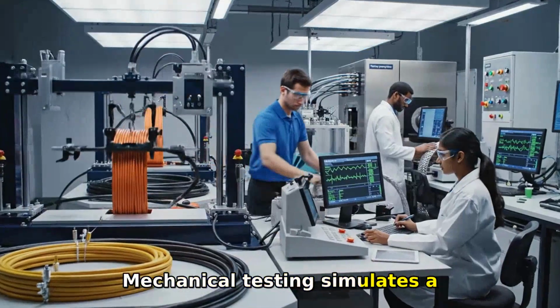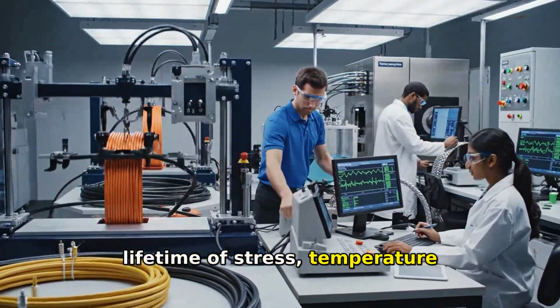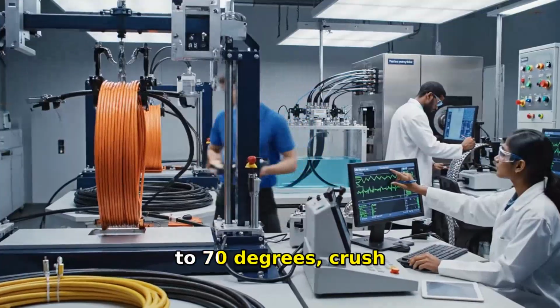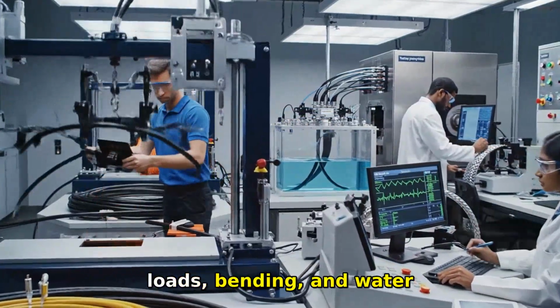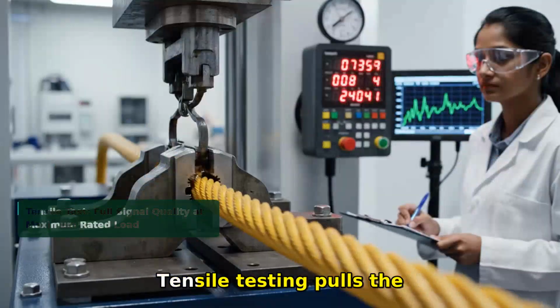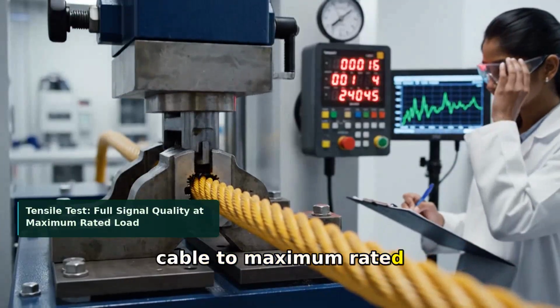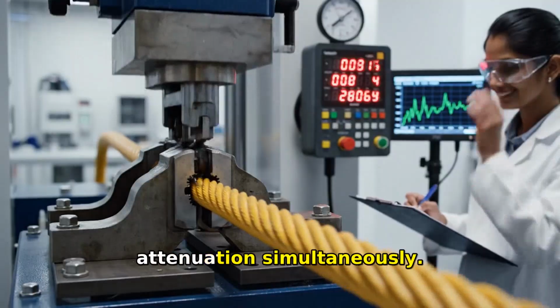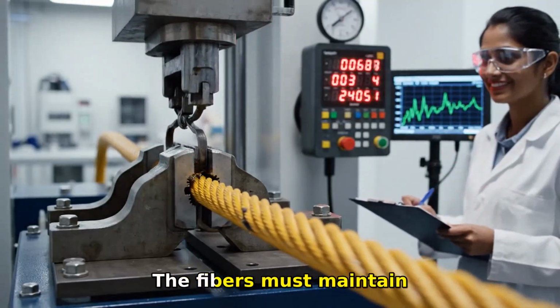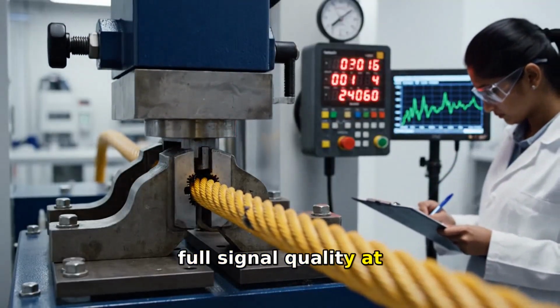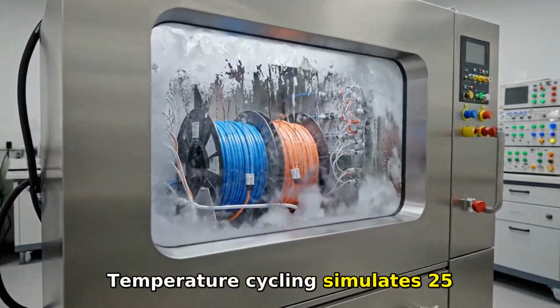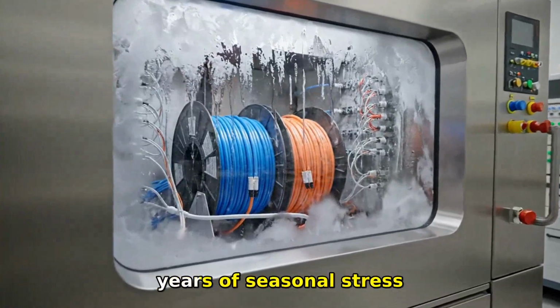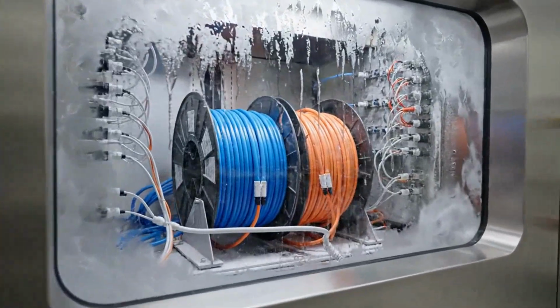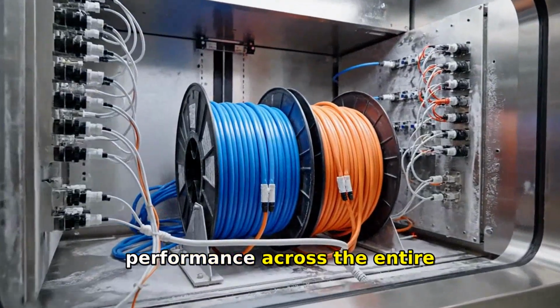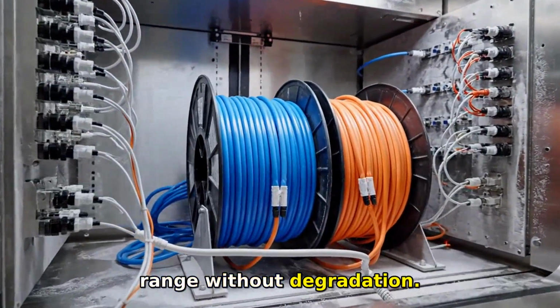Mechanical testing simulates a lifetime of stress, temperature cycling from -40 to 70 degrees, crush loads, bending, and water immersion. Tensile testing pulls the cable to maximum rated load while measuring optical attenuation simultaneously. The fibers must maintain full signal quality at peak stress. Temperature cycling simulates 25 years of seasonal stress in weeks. The fiber must maintain performance across the entire range without degradation.